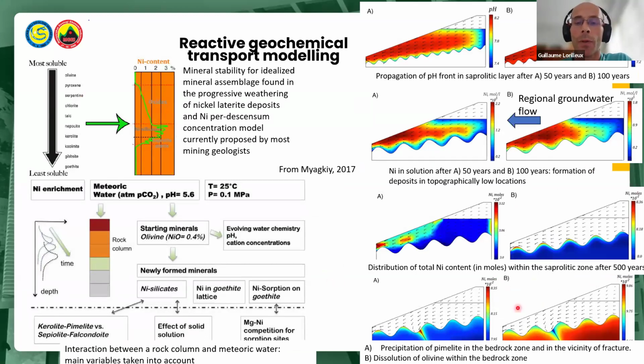Using reactive geochemical transport modeling, Myagkiy in 2017 was able to model lateral nickel remobilization and deposition and explain local nickel enrichments in topographically low areas and precipitation of garnierite in fractures. He showed the importance of the downward progression of the pH front governing nickel enrichments as shown on this diagram. So on the left part here, these are some of the parameters and variables that were used for the simulation. And on the right, there are some of the results.